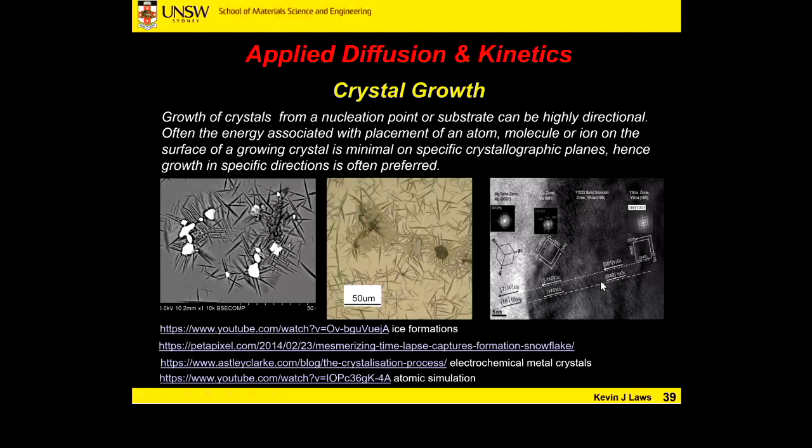What happens is the crystallographic plane of FCC copper lines up perfectly with another crystallographic plane of the Y2O3. So that's a low energy site for the copper to deposit, and it does so preferentially as we're cooling. We've only got a little bit of copper in this alloy. As soon as conditions are right, on top of that very thin layer of copper surrounding those particles, we're talking nanometers here, one of the prismatic planes of magnesium, the 1010 plane, is very low energy to deposit onto that plane of copper. And it does so very, very rapidly.